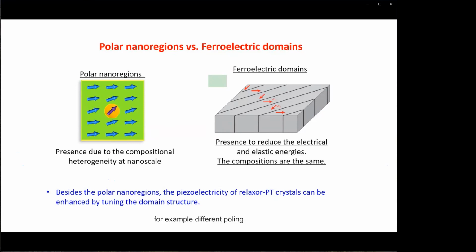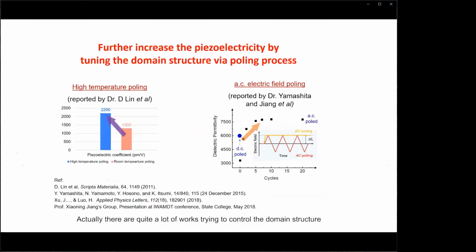For example, a different poling process or a specific annealing process by which we can change the size of domains. Actually, there are quite a lot of works trying to control the domain structure of relaxor ferroelectrics by poling process to further enhance the piezoelectricity. For example, Dr. D. Lin used high-temperature poling to engineer the domain structure of PIN-PMN-PT crystals, and they achieved about 70% enhancement of piezoelectricity of the crystal.